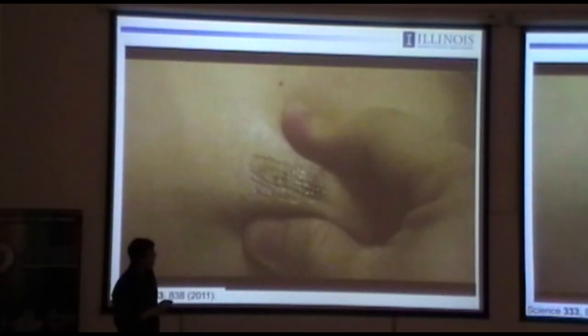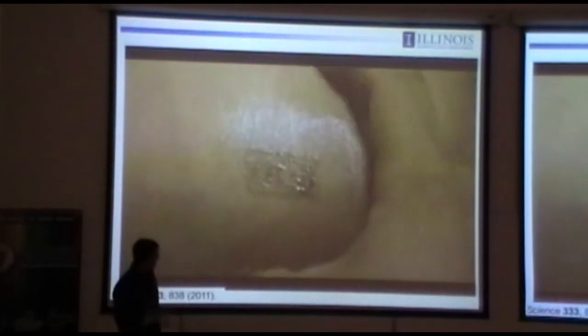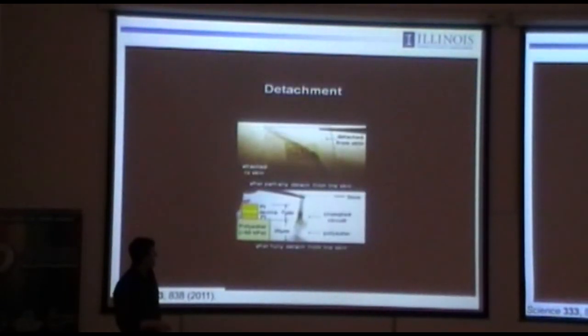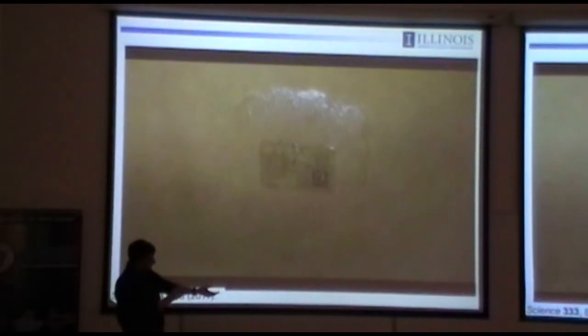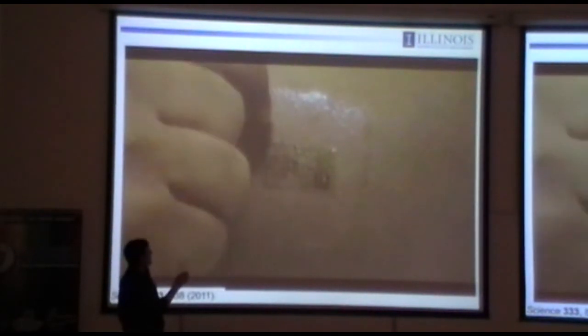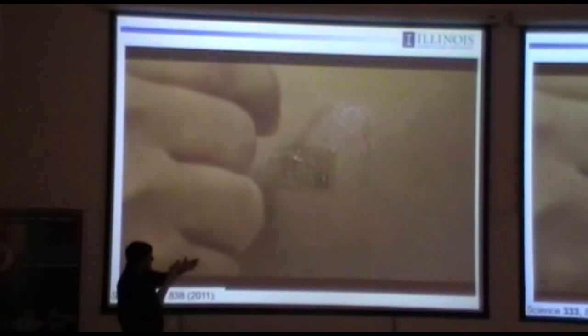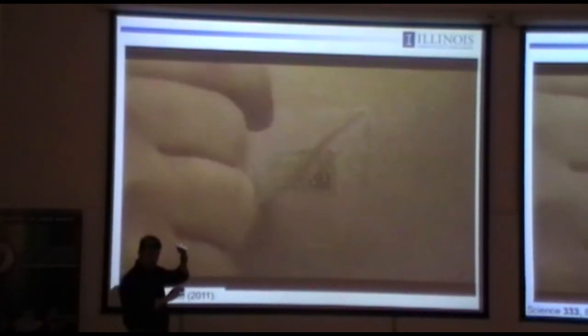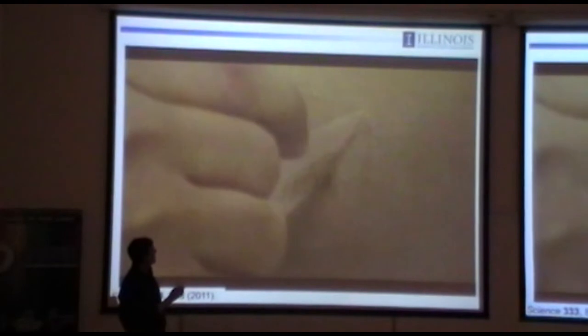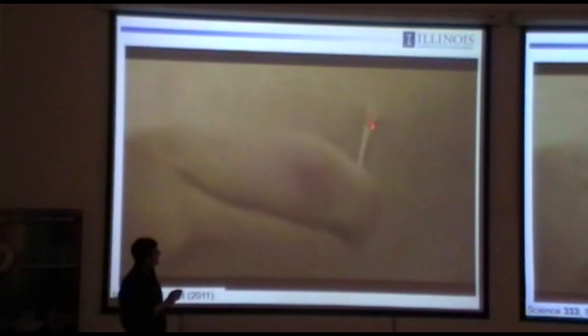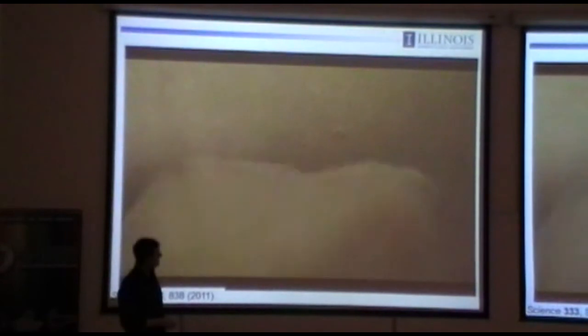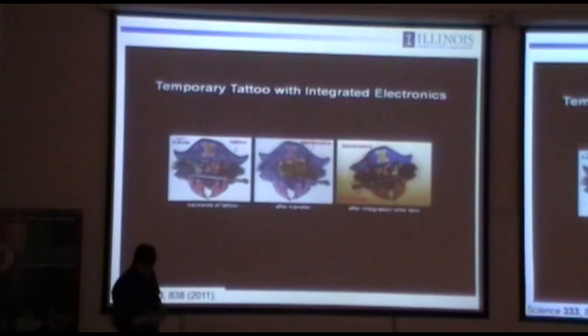And that's by design. So the circuit is not mechanically loading the skin at all, and that's consistent with finite element modeling of the mechanics. So again, as I mentioned before, it is van der Waals adhered, it stays adhered when you pinch, but the absolute value of the adhesion is not high. It's just the fact that we've driven the interface stresses down to these very low levels by going to this very thin, low modulus geometry. As a result, you can grab it by the edge and just peel it off pretty easily. It doesn't even tug on the skin that much, except at funny points like that, which I don't really understand. But anyway, it eventually comes off, and you'll have a chance to see what it looks like. And somewhat disgusting, but you know, it's like a piece of skin.